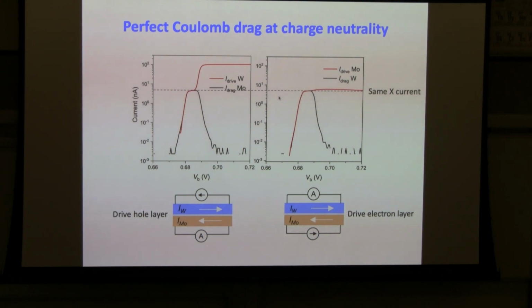So we can also do better. What I've been telling you is that we drive the electron layer and measure the hole layer, which is this kind of result here. This is from a different device. And we can also reverse the drive and the drag. We can drive the hole layer and measure the electron layer, and you get the same result. Over this window, you get perfect Coulomb drag, and then outside, you just get zero drag in the system.